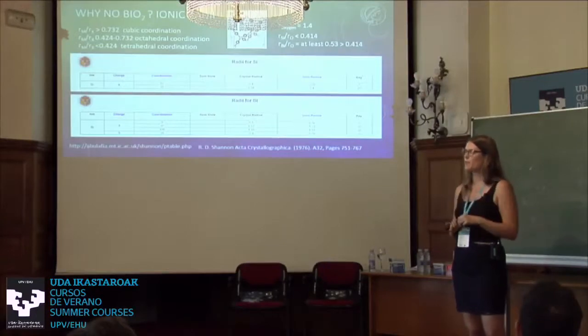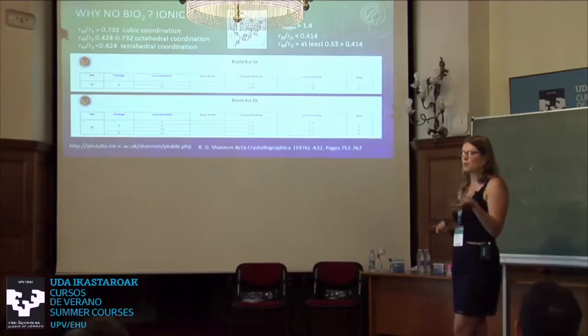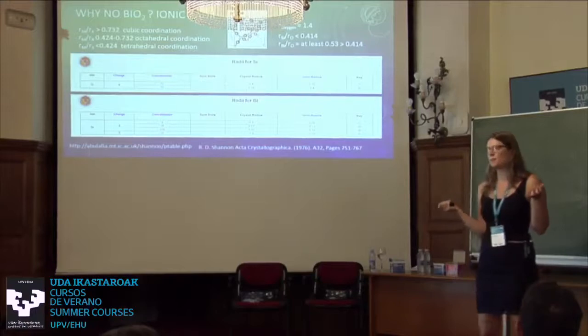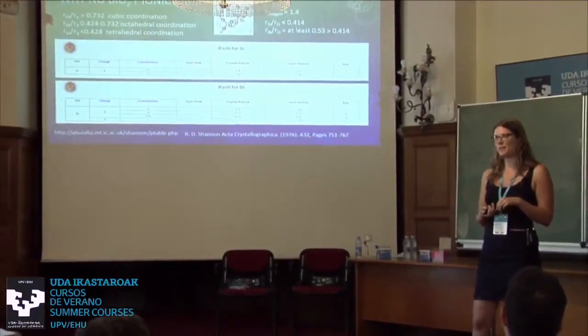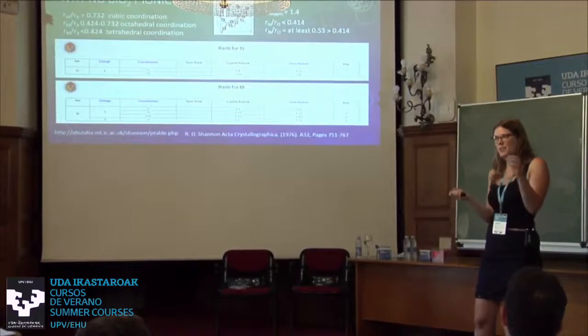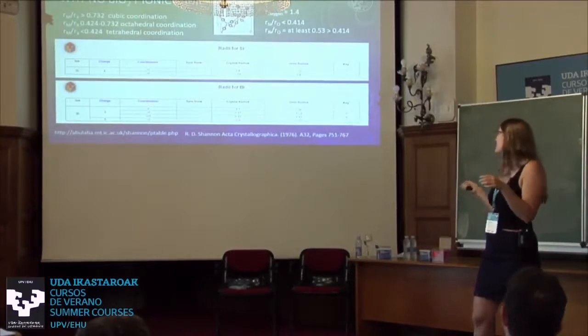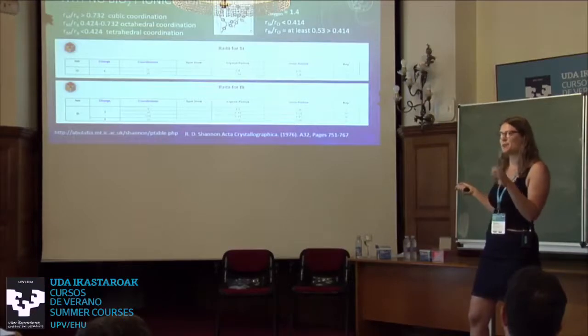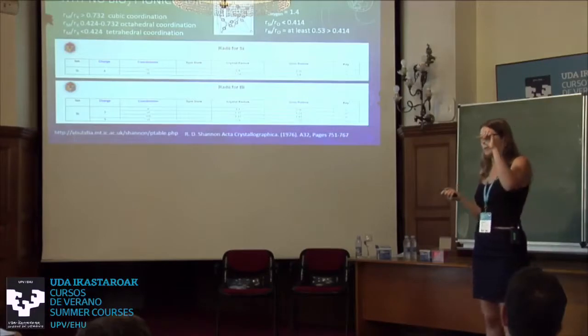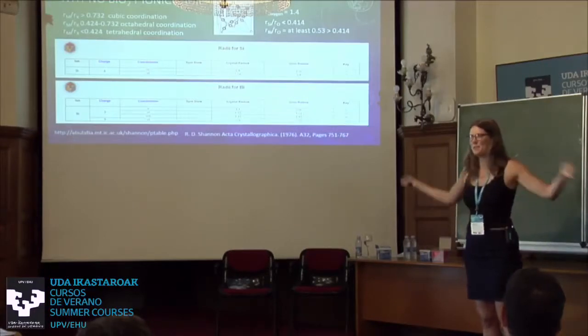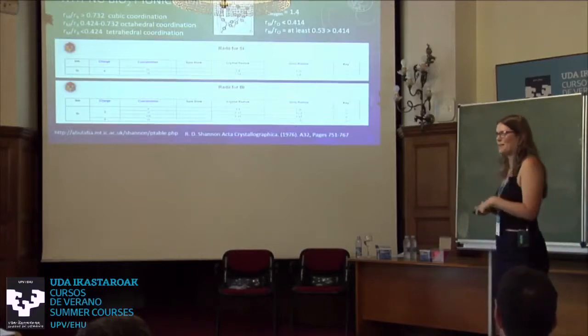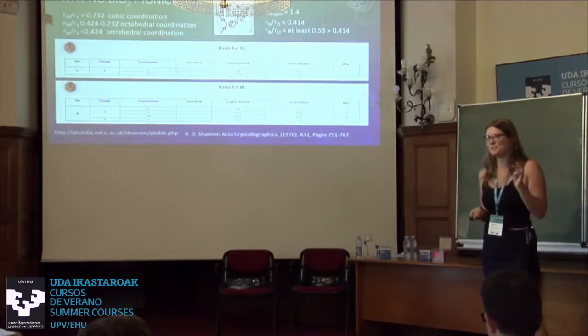Difficult. I mean, the problem is then you still would have to make the bismuth smaller. Maybe under very high pressure you can change the coordinations, but so far there's no known phase. So it would be listed here if bismuth would ever be observed in a tetrahedra. So I think you need to apply a lot of pressure. Pressure does give you a little bit of leverage, but this is a lot larger, and it's also for bismuth 5 plus, so it's smaller than 4 plus. So pressure pushes you a little bit about the boundaries of the phase diagram, but doesn't give you a huge change. Maybe if you apply pressures like in the core of Jupiter or something, but yeah.